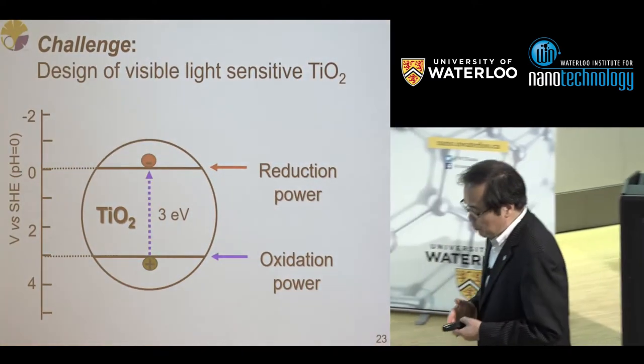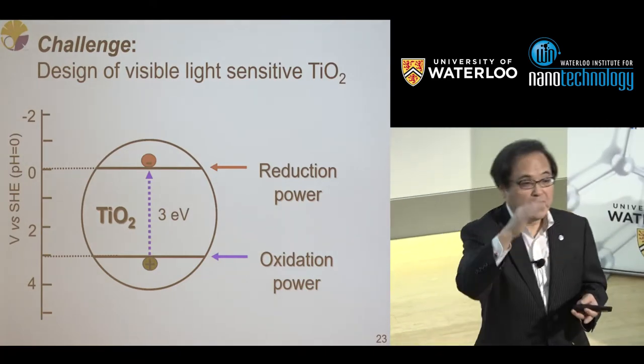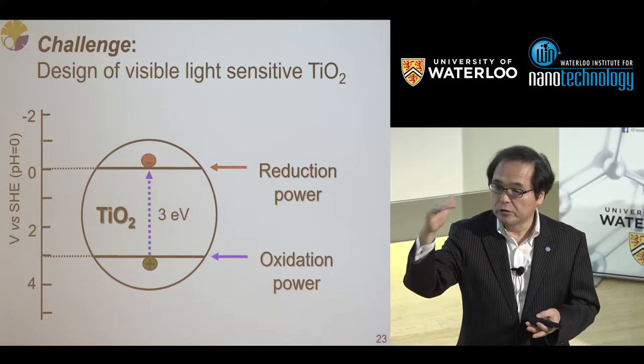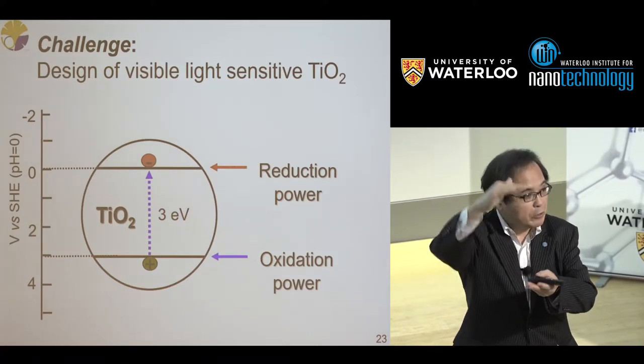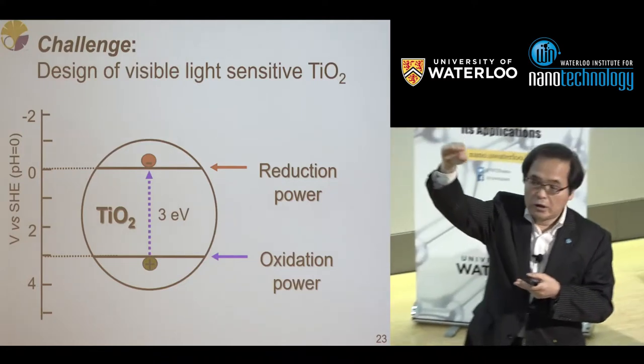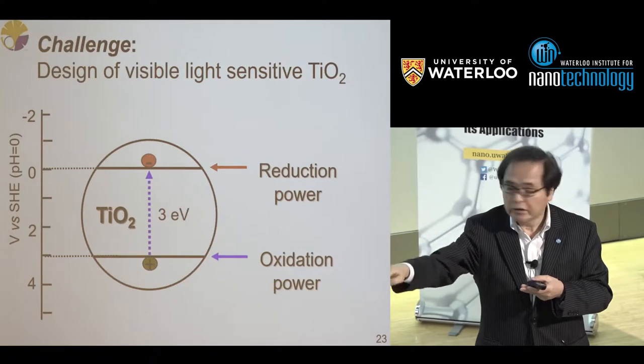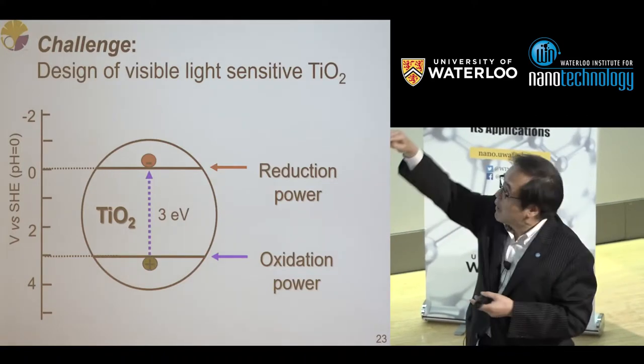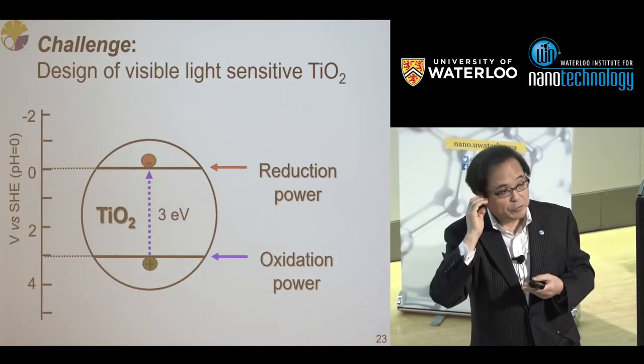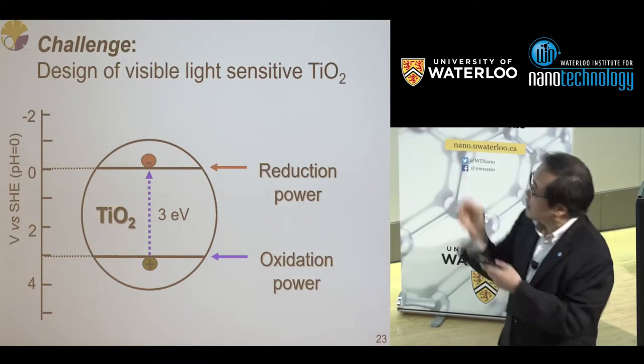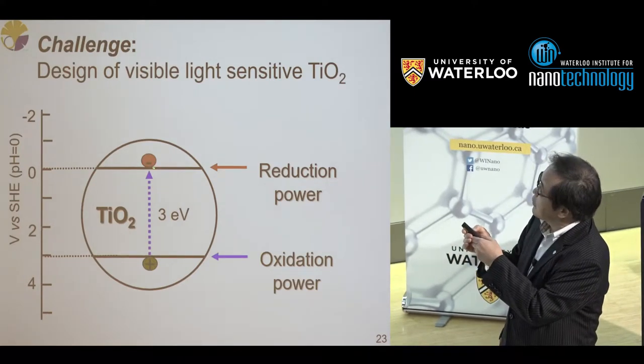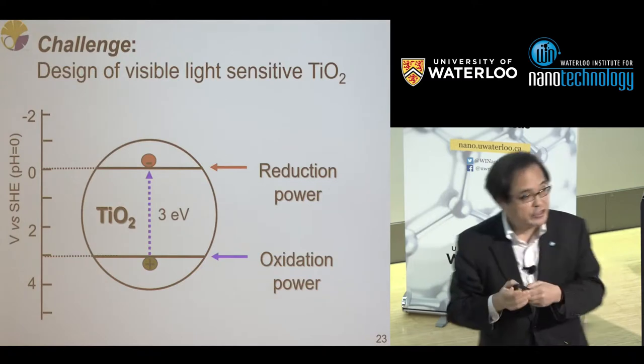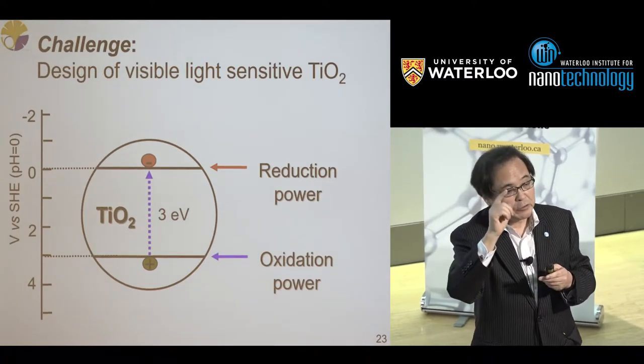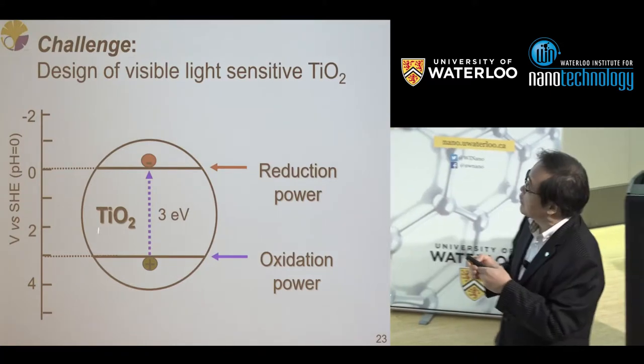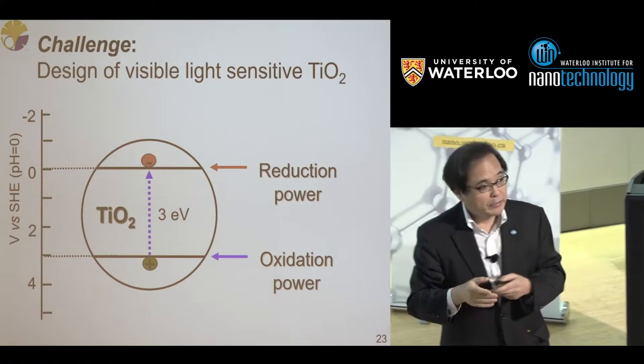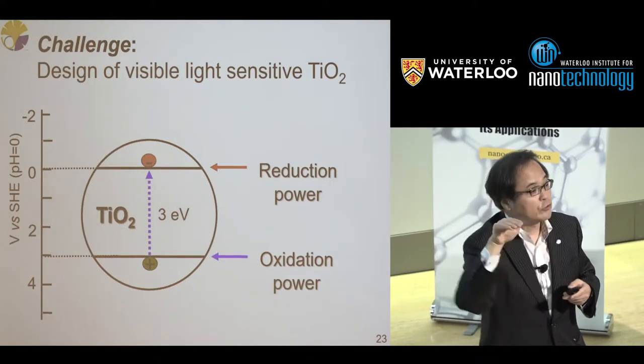So as I told, the band gap of titanium dioxide is 3 eV. We need UV light. To utilize visible light, we have to narrow the band gap. To narrow the band gap, there are two ways. One is to lower the conduction band. The other is to raise the valence band. When we lower the conduction band, the reduction power is decreased. And the excited electron, in our case, is consumed by reacting with oxygen. The one-electron reduction potential of oxygen is located very close to this conduction band position. That's why when we lower the conduction band, it doesn't work anymore.